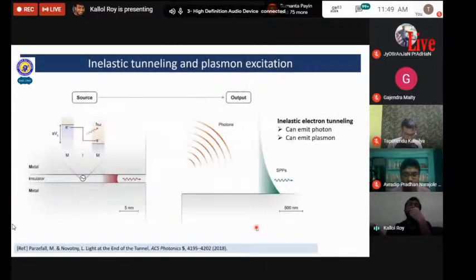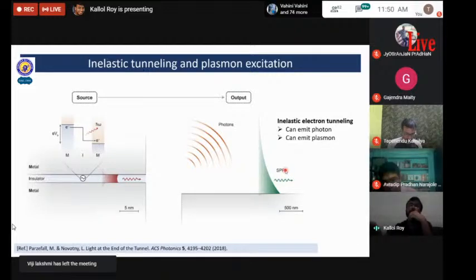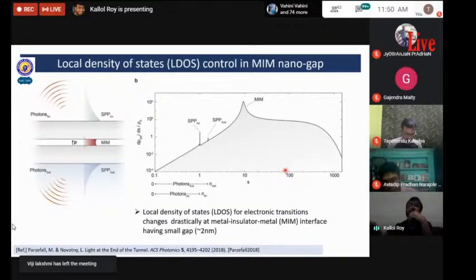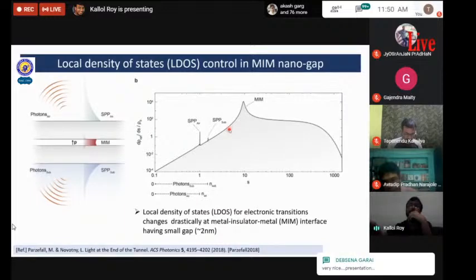And finally, I'll quickly show what we are doing here. It's basically inelastic tunneling, which I mentioned earlier. When an electron is coming from one electrode to the other across a small gap, then light can come out. Or another phenomenon can also happen: it can excite a plasmon as well. So we take this inside a metal MIM structure, where the density of states can be very high, and using this idea, we have efficient plasmonic excitation.